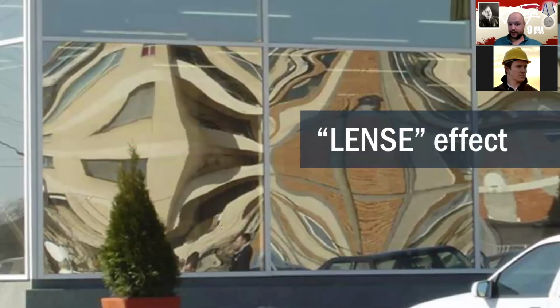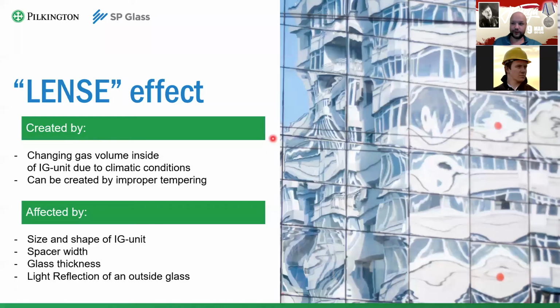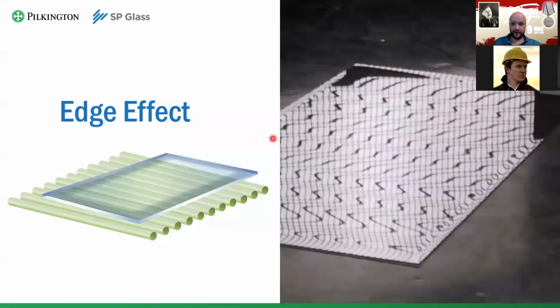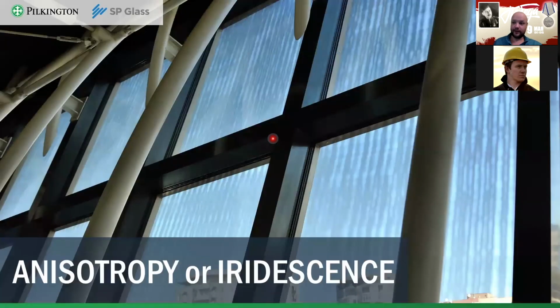That's the difference between lens and this thing. Lens is all around the edge of the unit, everywhere. Glass is bent, almost uniformly bent everywhere. And these central distortions are always in the center. They are always on the axis with the tempering. And they're always very sharp, very visible. A lot of people, by the way, don't know about them, mostly because they are quite a rarity these days, fortunately. So you'll not see them that often. I hope I answered the question. If not, just feel free to correct me.